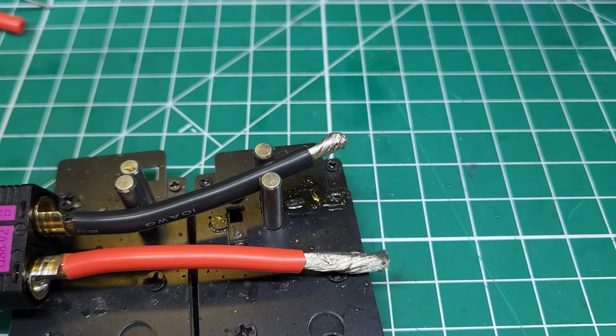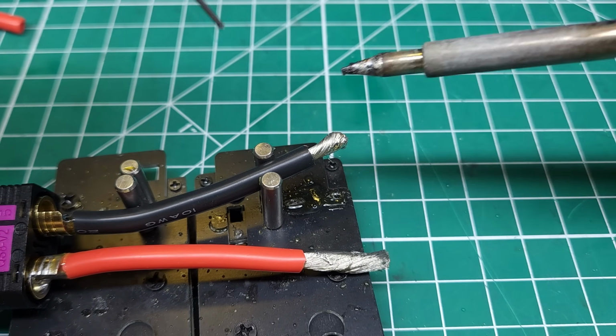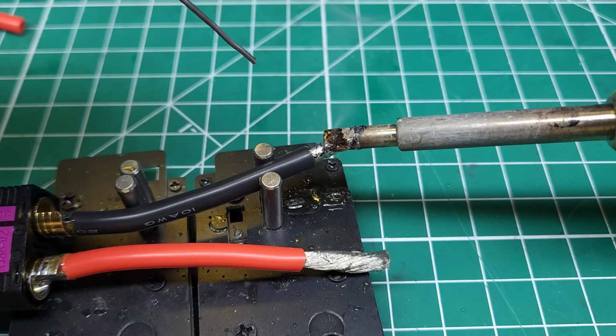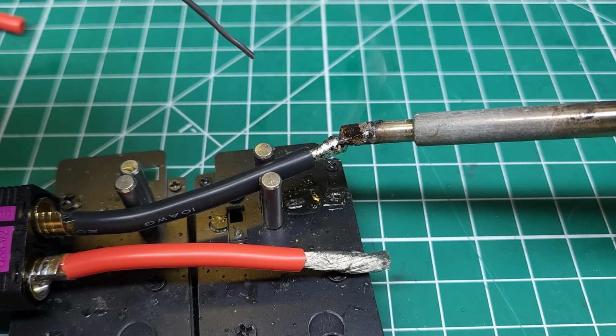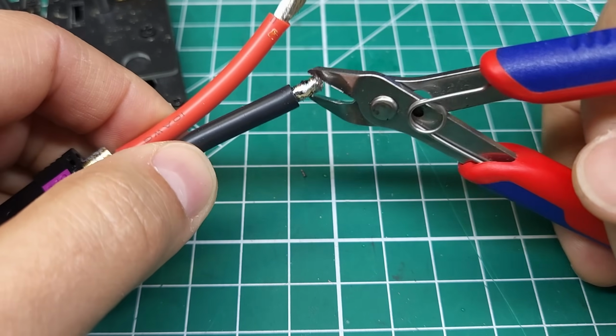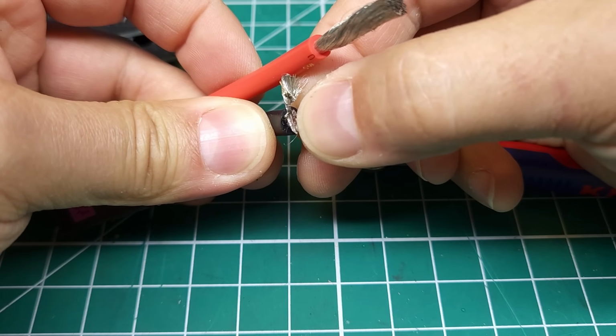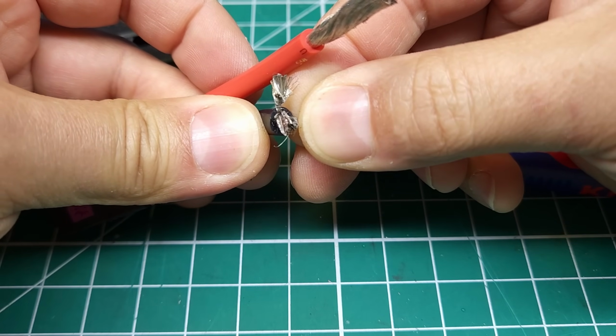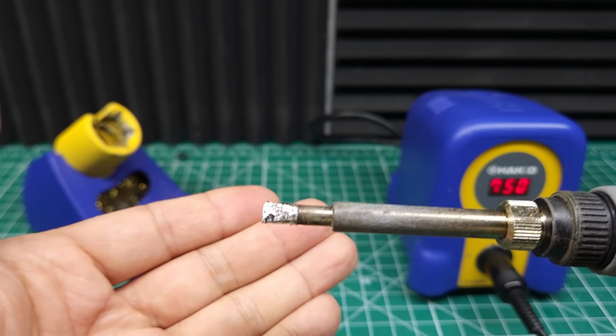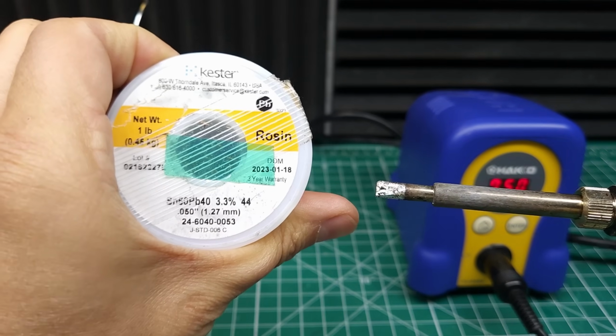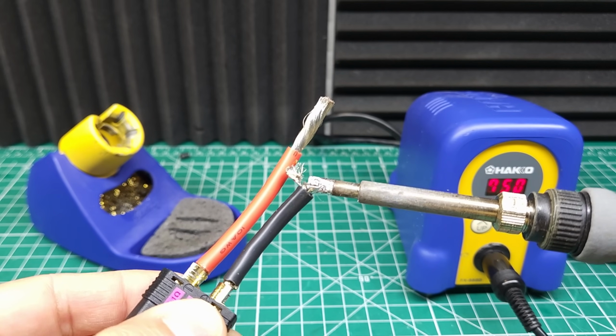No problem though, we'll just go ahead and put some solder on the bottom as well, right? And now we've got the bottom all nice and wetted too. Looks really, really good. But now if I cut this open at an angle, you can see we didn't actually get solder all the way through. And that's in spite of the fact that I'm using the widest tip you can get for this Hakko iron. I'm using very good lead-based solder, and I had the iron on there for plenty of time.